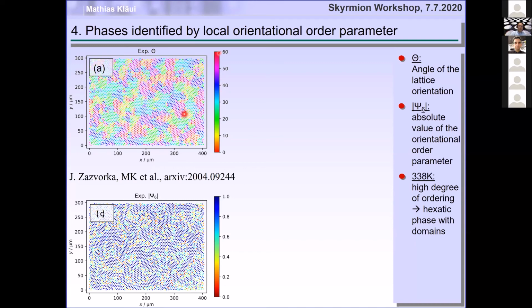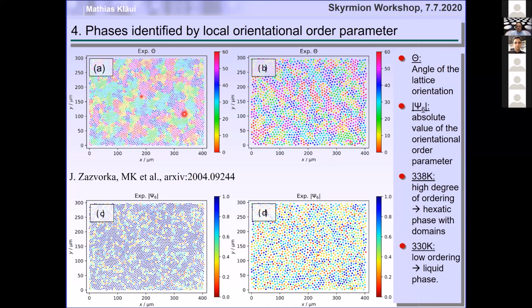And we see that this nucleation occurs by the crystallization of crystallites of the order of 20-30 skyrmions. And that's something that I found very cool. You can look at the crystallization of a lattice. And you see also here for the less ordered case at lower temperatures, there are very, very small domains. In general, the ordering is very poor.